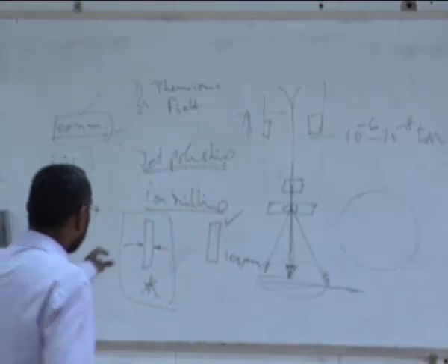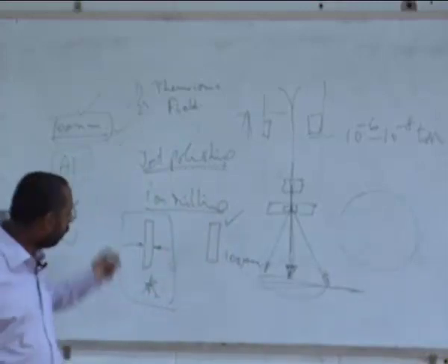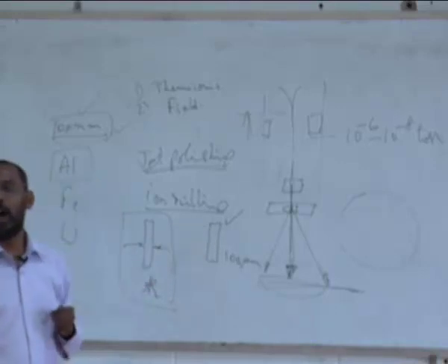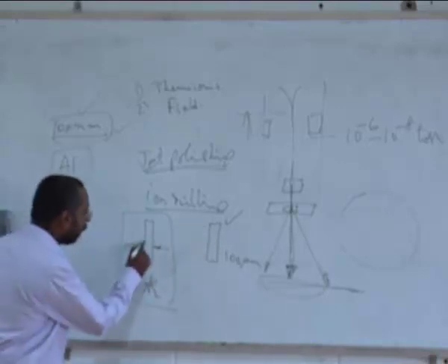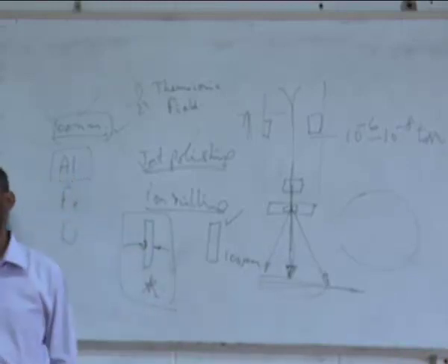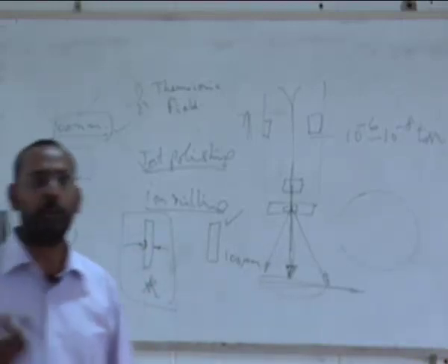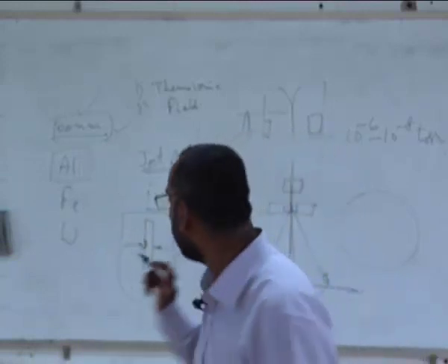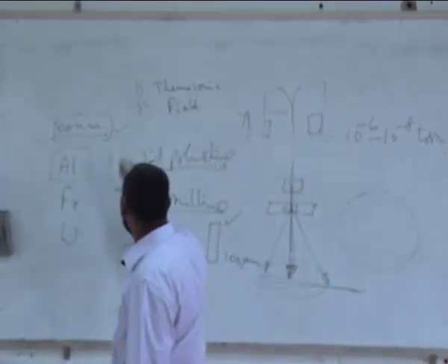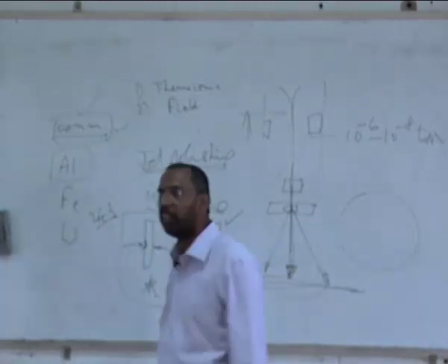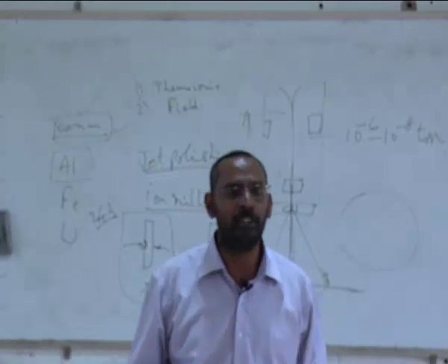So we do this by bombarding an ion beam onto the sample so that atoms are removed, sputtered away, atom by atom. Obviously, because this is happening atom by atom, it is a very slow process. For example, taking a sample from 100 microns to 100 nanometers might take about 24 hours. Whereas jet polishing is just a 2 or 3 minute job.